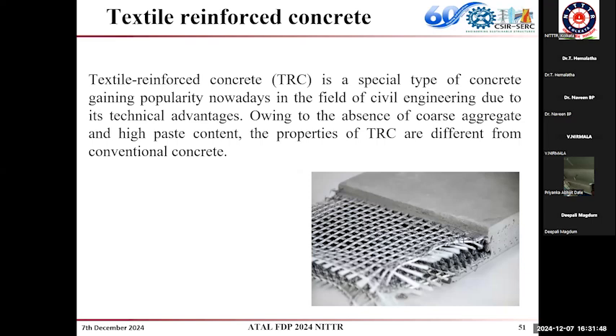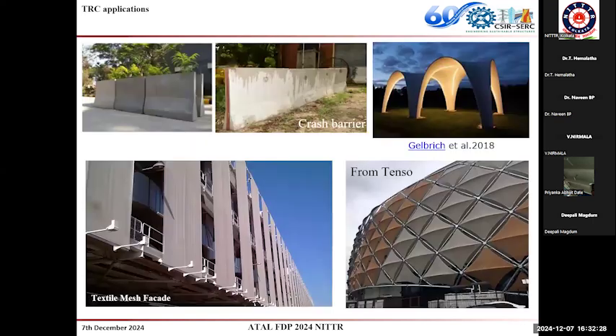Here the ingredients for the textile reinforced concrete do not include coarse aggregate. So we can make it even from 10 mm thickness. This textile reinforced concrete can be made at 10 mm thickness without compromising the strength. So this is contributing towards circular economy by way of minimizing the material which is needed. Another thing is it is non-corrosive in nature. So the life of this kind of concrete can be extended, or the durability is high.